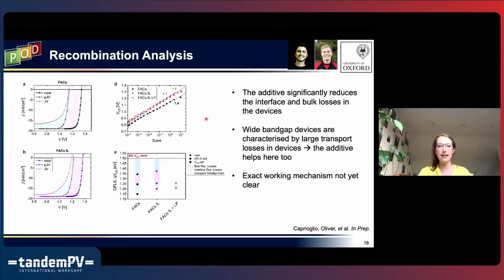So if we do kind of a full analysis of our recombination in this case, here we have, by using the PLQY as a function of flux, we can extract a JV curve of what we would expect for just the pure material. So this is just a neat FA cesium film. The JV curve has been simulated using the data collected from the PL as a function of flux. So going from kind of this black curve to this darker gray, this purple kind of shading in between, then we're looking at the simulated JV curve, or this pseudo JV curve, when we have the contact layers deposited, so doing the PL dependence with the contact layers deposited, and then compared to gray here is the actual device.